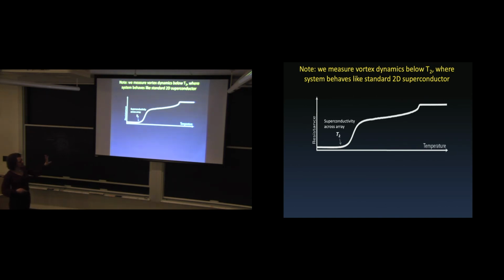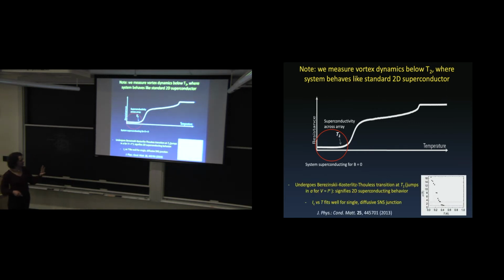And just to note, when I'm talking about the vortices, we're actually measuring in the superconducting regime. So before I was talking about up here on this phase diagram, now we're looking in the region where it's really superconducting and then applying a magnetic field, just to differentiate. And for people, right, so here, it's superconducting at zero field. And for people who care, it really acts like a Kosterlitz-Thouless type system here. It's a real 2D system where we've looked at how the exponents change for the IV curves.